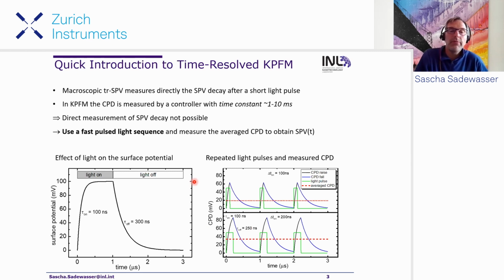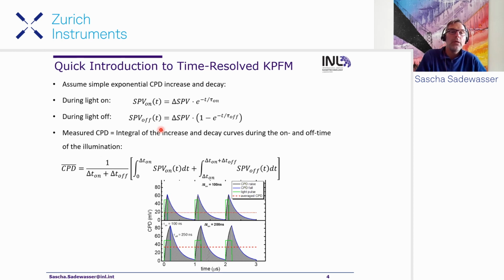And in the end, by varying the pulse durations, we can get a spectrum that has meaningful information. For this, you can just assume, for example, a simple exponential rise and an exponential decay, and then do a little bit of simple math, and you can essentially estimate your average CPD, and it contains information on the time constants of these two processes.